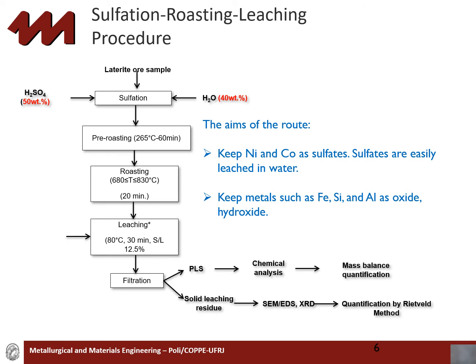So after the sample's heat treatment, the sample is cooled to room temperature and finally leached with water. During leaching, water-soluble sulfate dissociates, leaving metallic ions in solution. Iron, after heat treatment, tends to remain as oxide, which presents low solubility in low acid water solution. So, iron concentration in the pregnant leach solutions is low. And finally, the filtration of the leached product will give us a PLS, which is the pregnant leach solution, and the solid leaching residue.